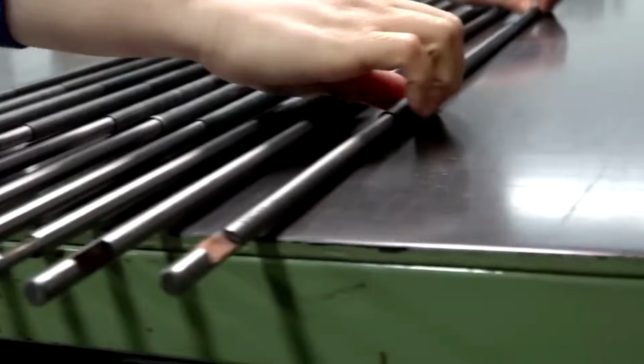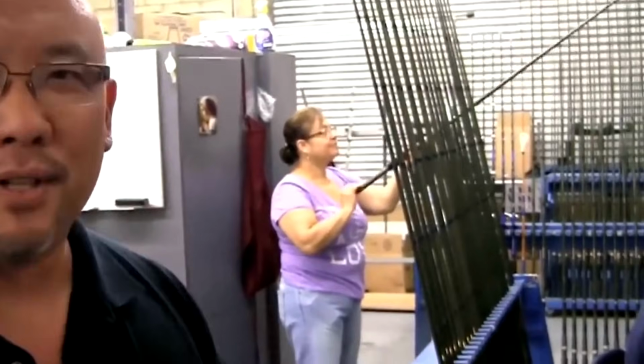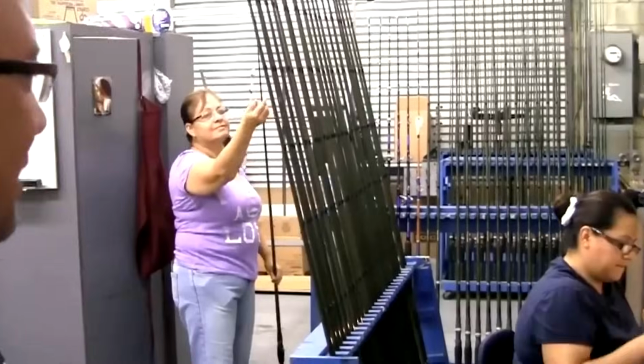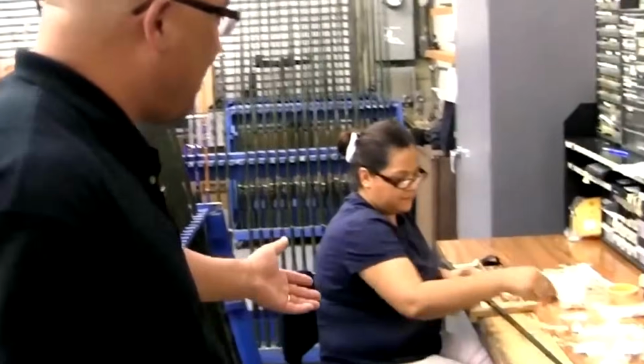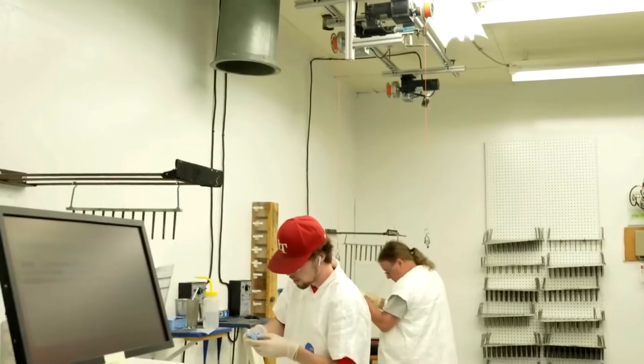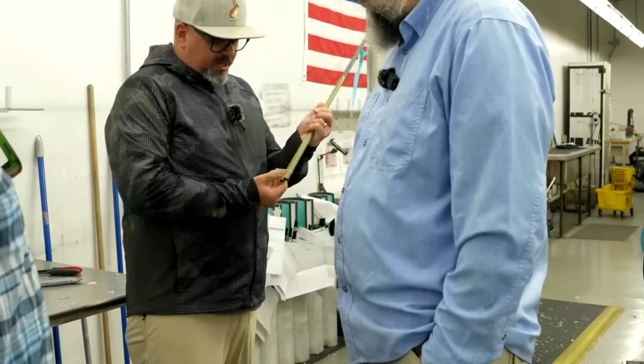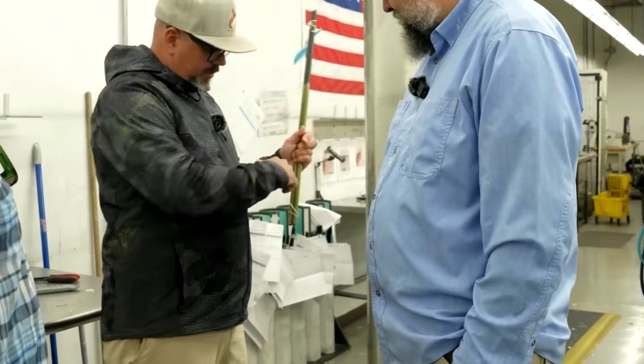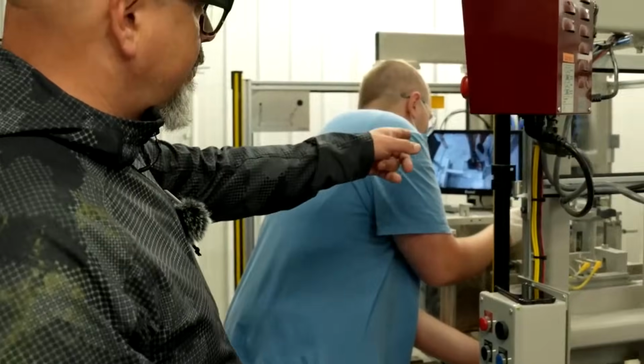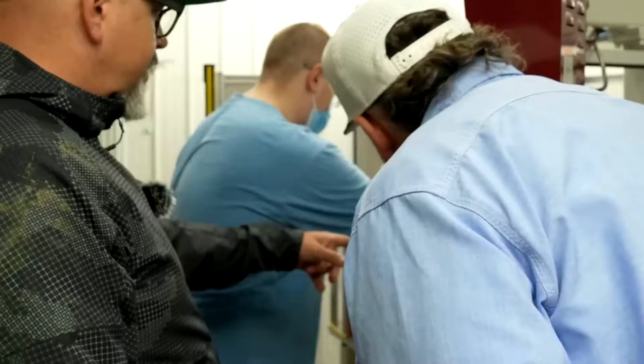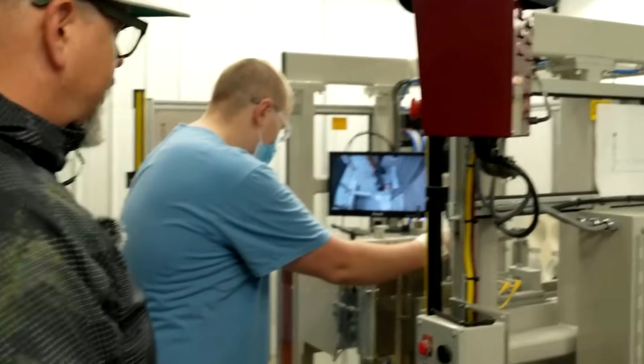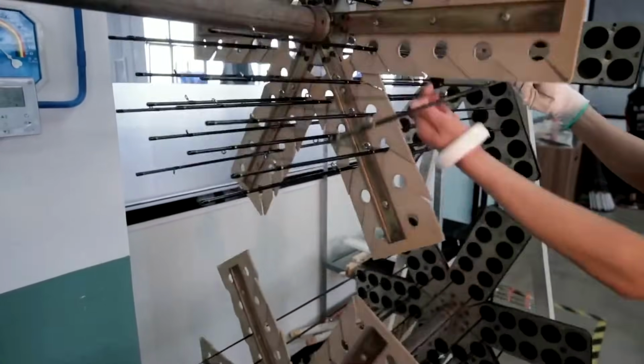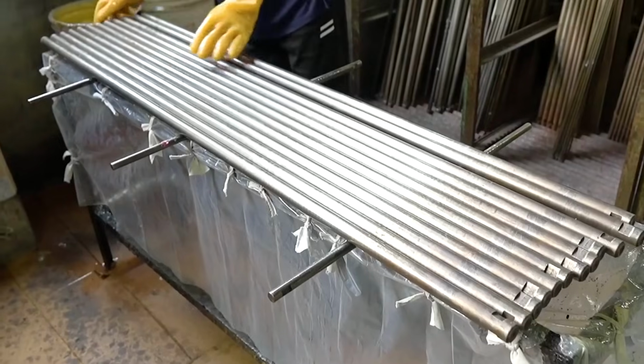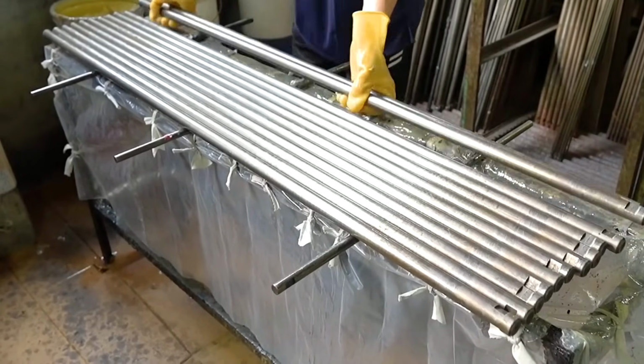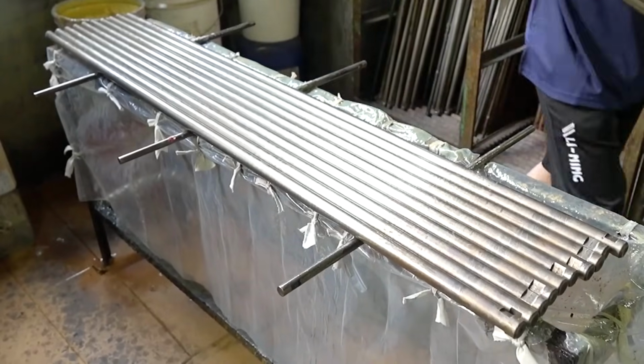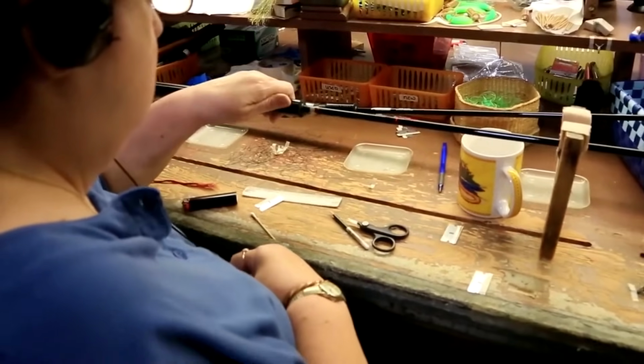Each carbon piece is aligned with meticulous care along the mandrel's central axis, ensuring the edges are perfectly squared at both the tip and the butt ends before being secured. If this foundational layer is even slightly off-center, the entire rod blank will inherit that misalignment, compounding the error through every subsequent wrap. There are no automated robots or laser guidance systems involved in this critical phase. Everything depends entirely on the technician's trained eye and years of manual experience.